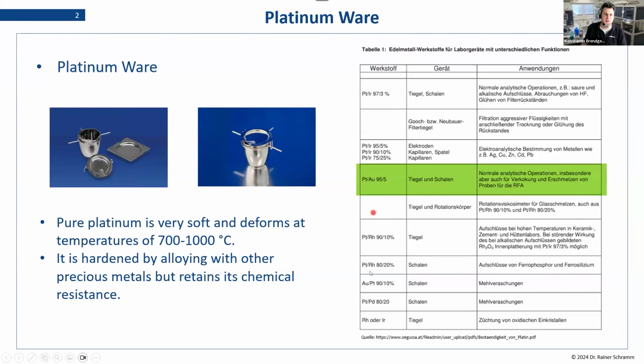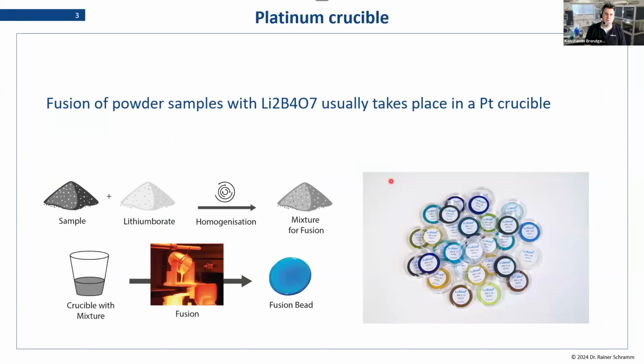There is a little list here of different alloys that are used commonly in laboratories. So there is iridium, there is some rhodium added. We in our laboratory here at FLUXANA are using these vessels mostly for fusion applications, doing these tetraborate beads. We are using the platinum-gold alloy, which is 5% gold, 95% platinum. As I'm sure you're all aware, we're using samples and tetraborate in our fusion devices to make these nice fuse beads that we then analyze with the X-ray.